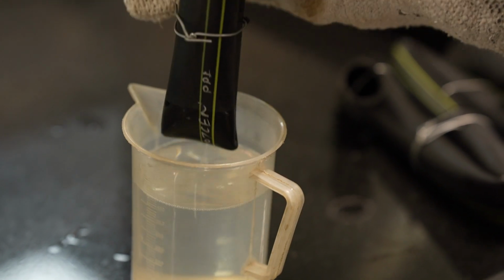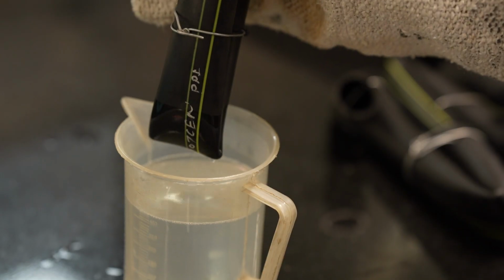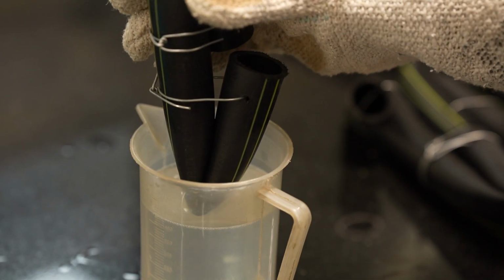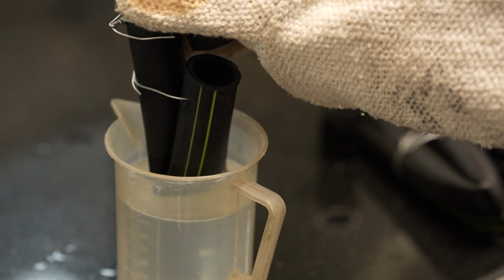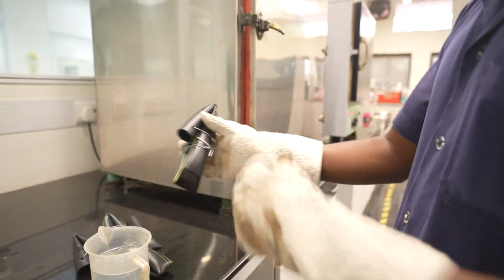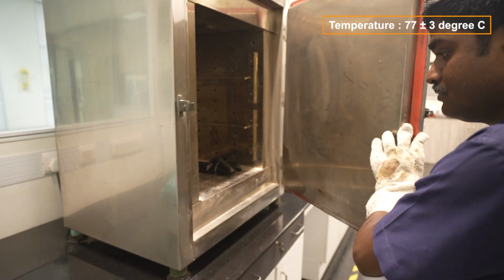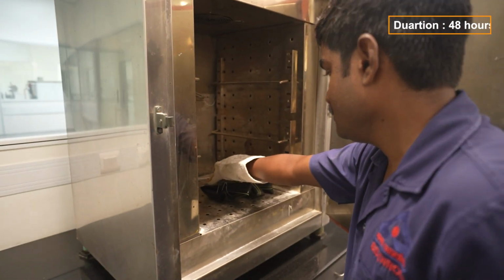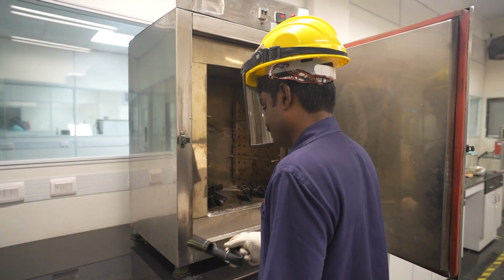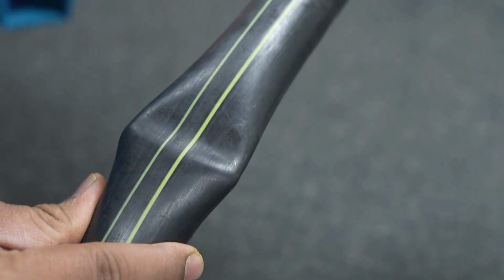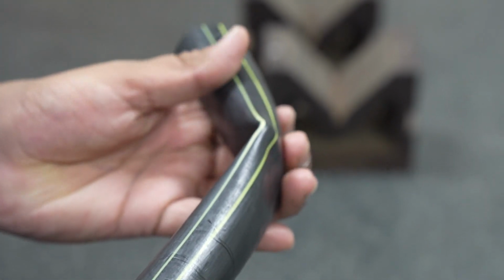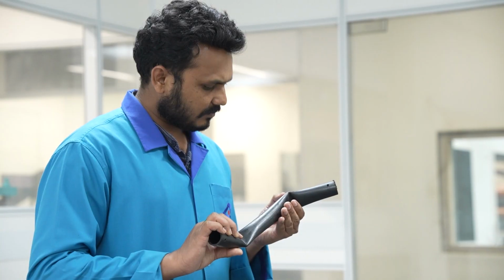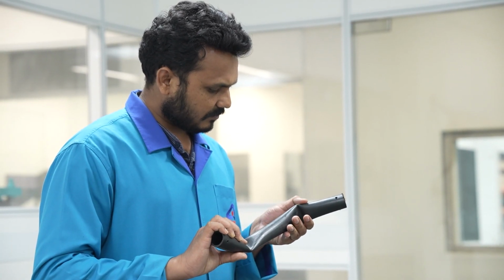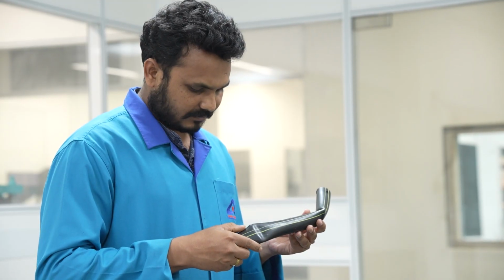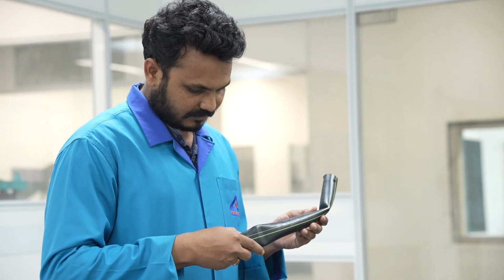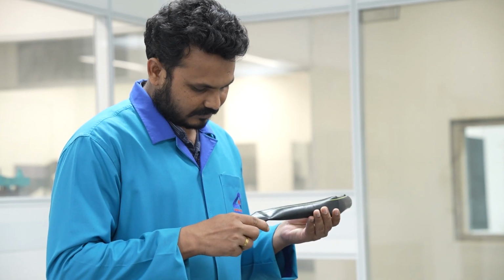According to the standard, the ESC test involves sharply bending 5 test specimens at both ends, coating them with a reagent and placing them in an oven at 77 plus minus 3 degrees Celsius for 48 hours. After 48 hours, the sample is removed and the samples are inspected for cracks to determine conformity. It will consider failure of the bends if any crackings, crazing, bloom or rupture in the bends. The pipe is considered to have passed the test if not more than 10% of the bends have failed.